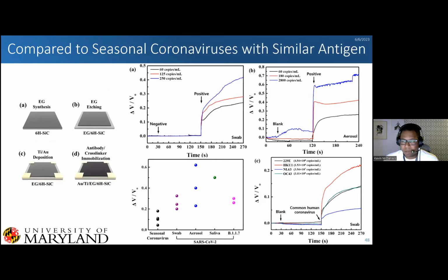And so, of course, one of the next things we did was look at other seasonal coronaviruses. And we're able to show that at extreme concentrations, so 10 to the 6, 10 to the 7, 10 to the 8 copies for these seasonal coronaviruses, yes, we do see a response because the spike protein is very similar to SARS-CoV-2, but we never reached over the 20% threshold that we set. This is compared to just 60 copies of SARS-CoV-2. We're getting responses higher than extreme copies of conventional ones.